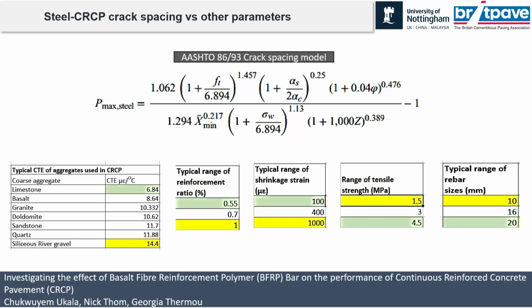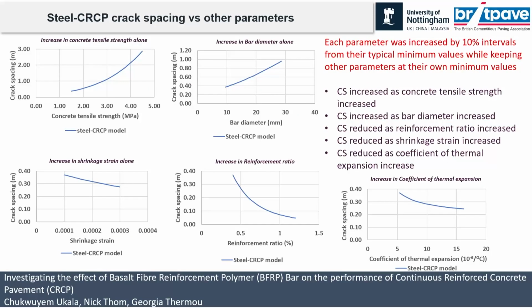So what we did was keep all these values at minimum. For example, using limestone, 0.55, 100 for the shrinkage, keep all the values at minimum, 1.5, 10, and put it inside here. Then we varied the parameter we wanted to test to see how much influence it had, from the minimum to the maximum, increasing it by 10% each time. So if only that parameter were to change, what would be the effect?